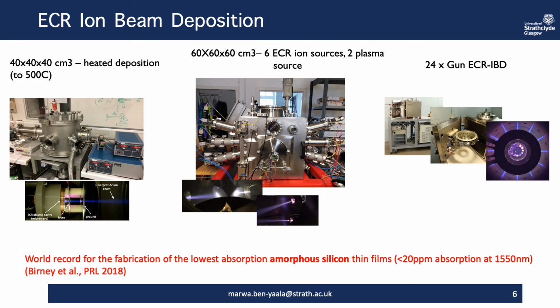So currently we are developing and using 3 different ECR systems for our coatings. The first one here is the one that has the capability to deposit at high temperatures, and this was the first system that demonstrated the world record in the fabrication of the lowest absorption amorphous silicon thin film, so less than 20 ppm at 1550 nanometer.